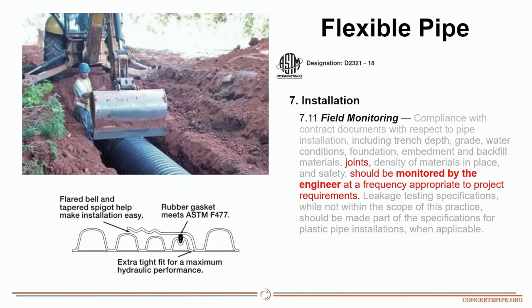The same temperature differential discussion with regards to manhole connections is also relevant to pipe joints as well. A 60-degree temperature change will cause a 20-foot length of HDPE pipe to shrink about 1 inch. Even if it's only a 30-degree temperature change, the pipe will shrink about a ½ inch in length. Keep an eye out for wide joints when reviewing post-installation videos.